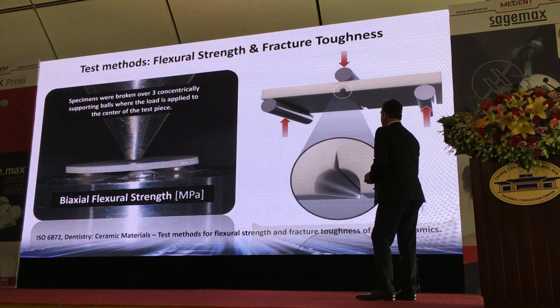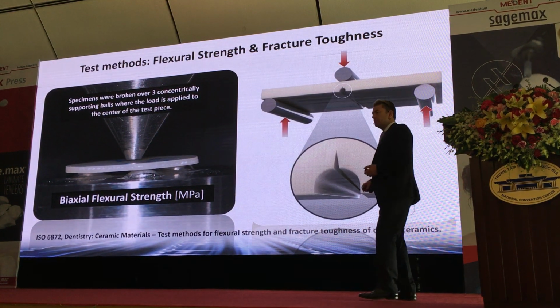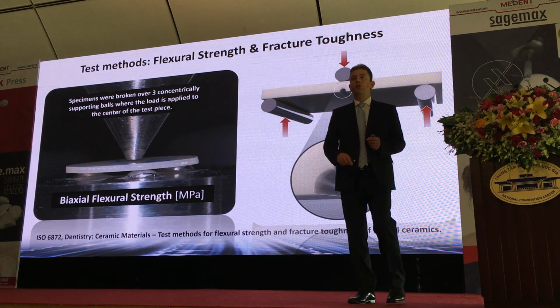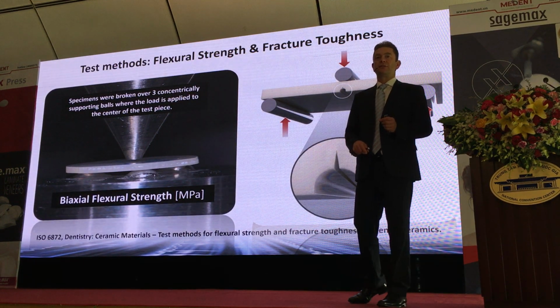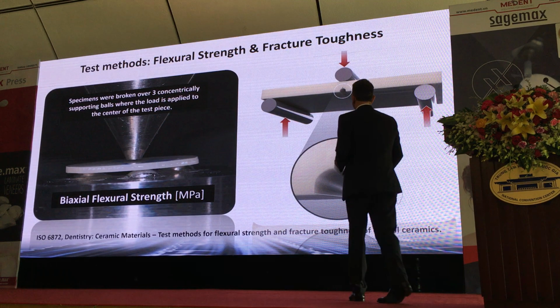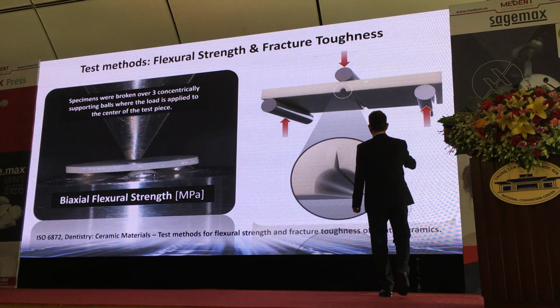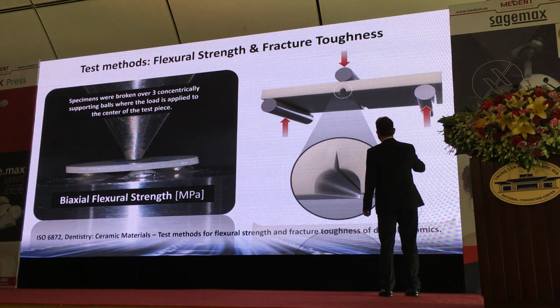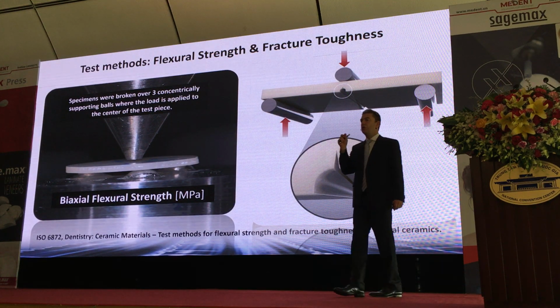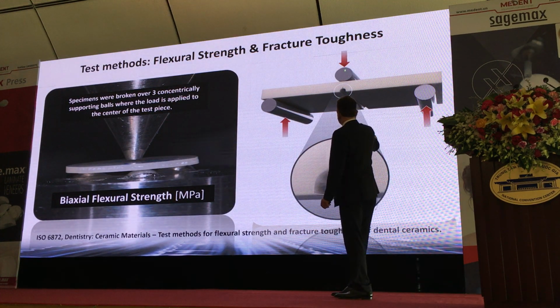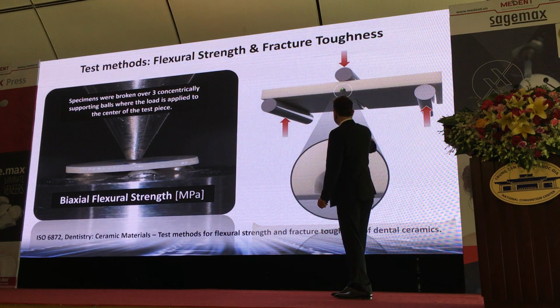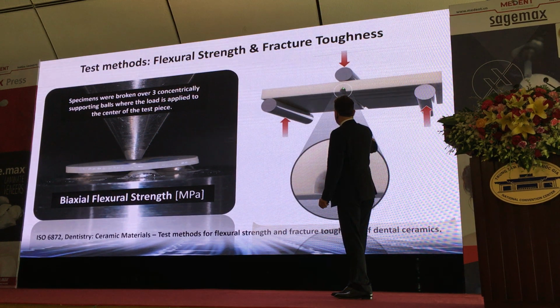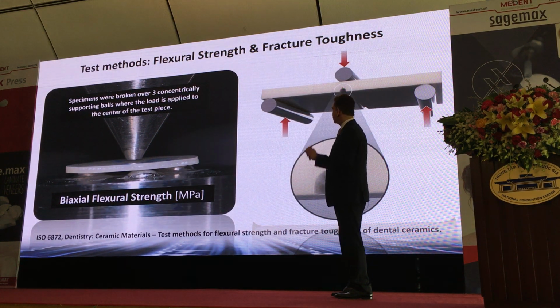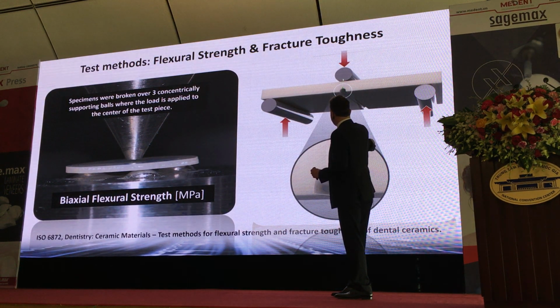And there's another very important test that we should look at. It's called fracture toughness. And the fracture toughness is measured like this. So we have the ceramic sample, and there is a little notch, right? Already a little notch. And if we load this, there is of course a lot of stress. So now we can measure how much force we need to crack this.